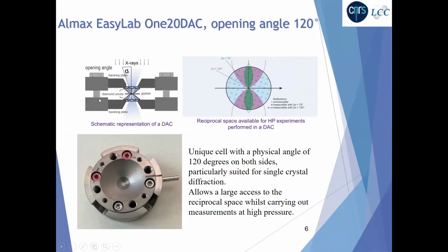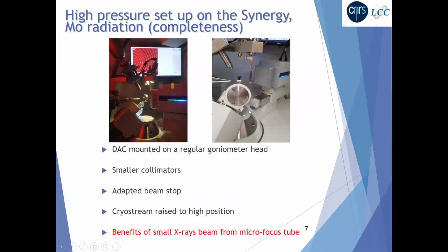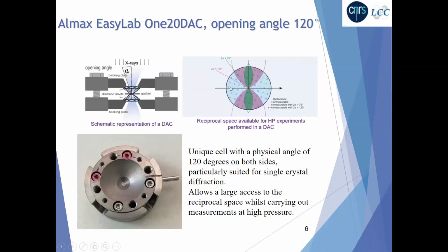So here is a schematic view of the DAC with the diamond here, the backplate, the opening angle. Here you have the gasket. In the middle, you put your crystal with the X-ray coming in and coming out. This unique cell with an opening angle of 120 degrees on both sides is particularly well suited for single crystal diffraction. So it allows a large access to the reciprocal space whilst carrying out measurements at high pressure.